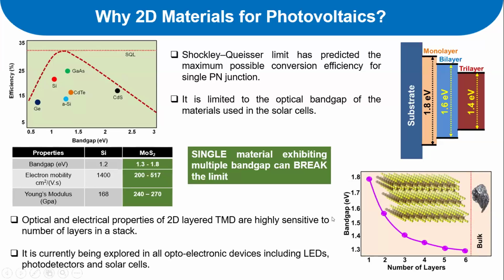So if we want to make a junction, and if we consider only one material and stack layers with different optical band gaps, then the Shockley-Queisser limit can be broken. The Shockley-Queisser limit is predicted based on the optical band gap. In this particular case, if the optical band gap of the material is highly variable, meaning it's different, then definitely the performance can also be boosted. So that is the basic idea in this particular case.